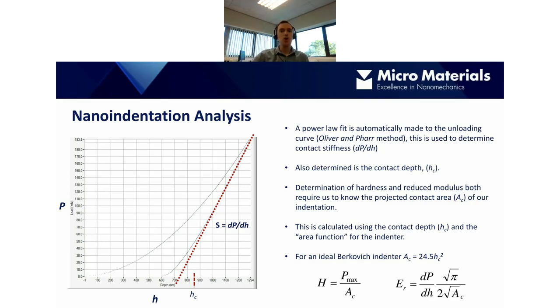You can see the hardness equation is very similar to that of the Vickers hardness, where it's the load divided by the area. But for the Vickers hardness, it's the residual area, so the area is measured after the indentation, and it's measured optically, of course. Whereas for indentation hardness, the hardness is defined under load, so it's looking at the contact area under the loading conditions. We're not using the imprint of the residual indentation.